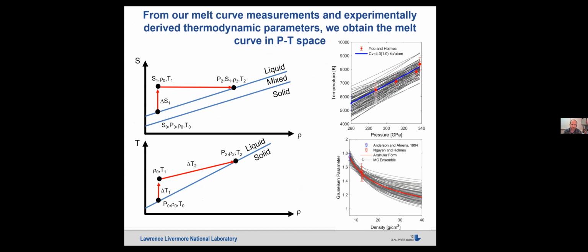All right, so the Brown and McQueen data, at least in the same pressure range, is pretty consistent with Nguyen and Holmes, except that the Brown and McQueen data is on an alloy. Forgetting the top of my head, I remember that being pretty consistent, although the Nguyen and Holmes data had smaller error bars, so I chose to fit to the smaller error bar data. I chose not to use the isentropic sound velocity data because it is expected that you have a slight change in gamma as you go from the solid to the liquid phase, and there is some slight temperature dependence. So I chose to use data that was as close to the same temperature or entropy as the experiment.